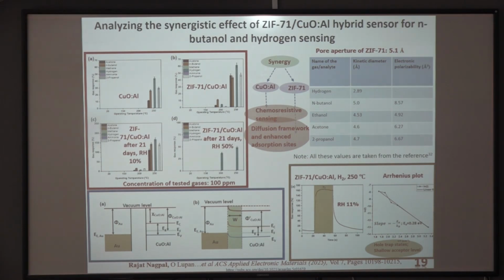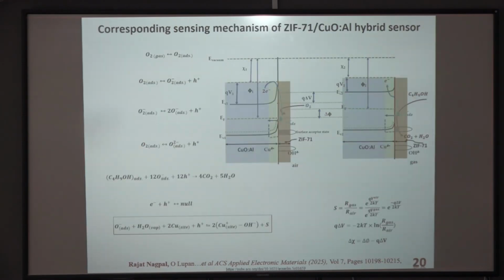So we have to use another concept. Here we can see, using electronic polarizability, N-butanol has appreciably high electronic polarizability compared to other VOCs, which gives information on how N-butanol is highly selective compared to other VOCs. And to get insights about the defect states, using an Arrhenius plot, activation energy was calculated, and its association with the hole trap states can be confirmed.